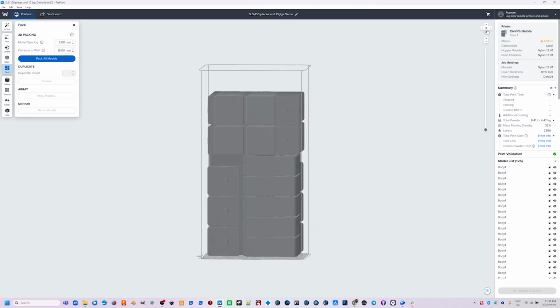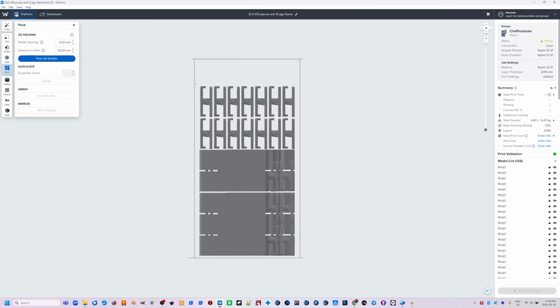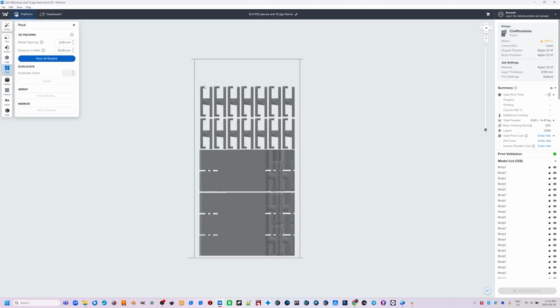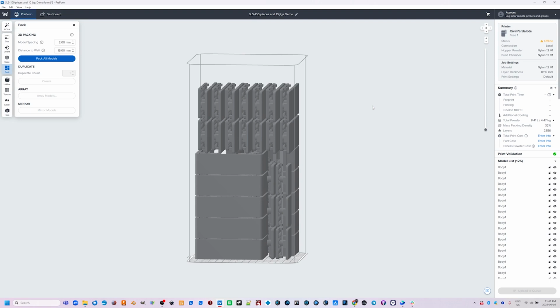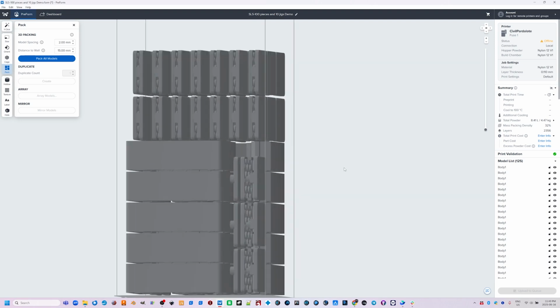Now, one thing you're going to notice, and I'll point this out here, is on the side and on the bottom here, you see that I have a bit of a gap, and this is done on purpose. The reason for this gap is that in Fuse prints, once the print is complete, you don't want to take the build chamber out right away because the build chamber is very hot. And if you take it out of the printer, the build chamber is going to cool rapidly. And what will happen is, because these parts are still hot, they can warp during the cool down process if they cool down too quickly.